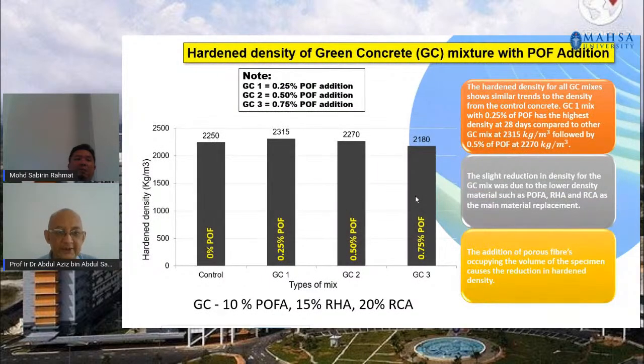Now this is the density of the green concrete with the palm oil fiber. So again, we did this study on the density of the green concrete with palm oil fiber. As you can see, the density of the concrete does not change that much. Very unfortunately, it doesn't change that much. At 0% palm oil, the green concrete at 0 fiber is 2250, whereas with 0.25% fiber, you have 2315. It adds up a bit more in terms of density.